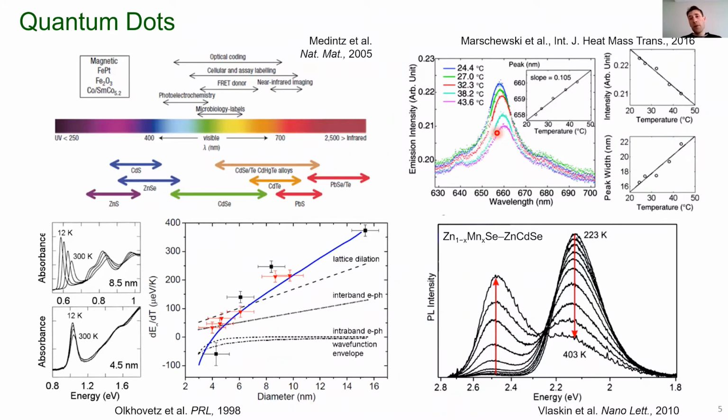And so if you just monitor the intensity of your emission, a drop in fluorescence might not necessarily mean an increase in temperature. It might mean that simply the light coming from your sensor has been absorbed or scattered. And so if you have a way of referencing your measurement to something else, then you are immune to scattering